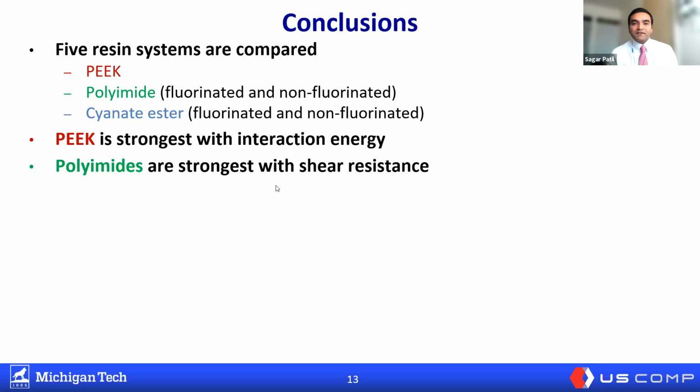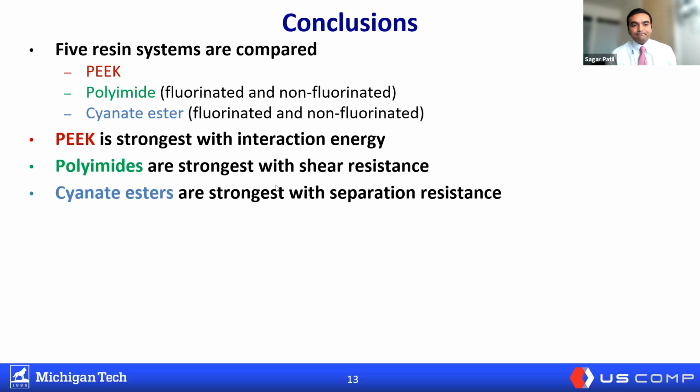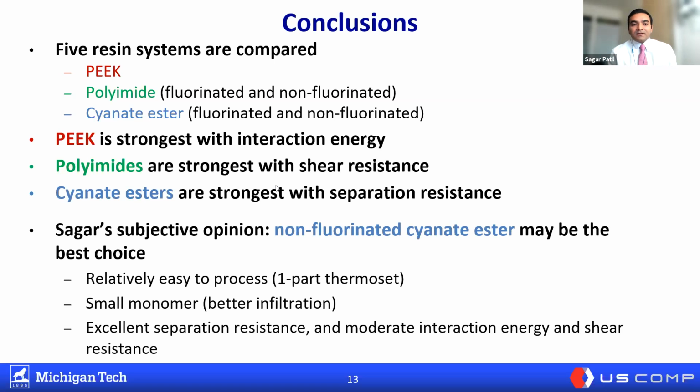Then we have polyimides, which offer the strongest shear resistance simply because they are very large molecules and offer steric hindrance because of their respective chemical groups. And then we have cyanate esters that offer the highest separation resistance. So to conclude, in my subjective opinion,